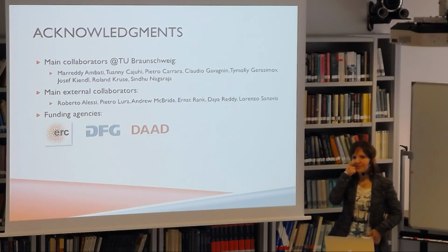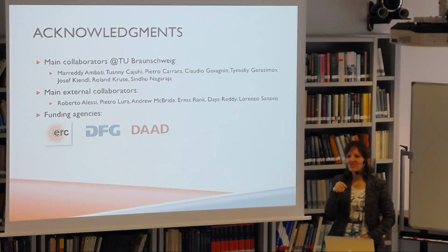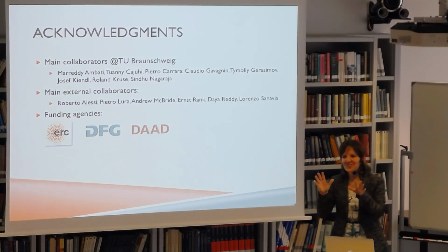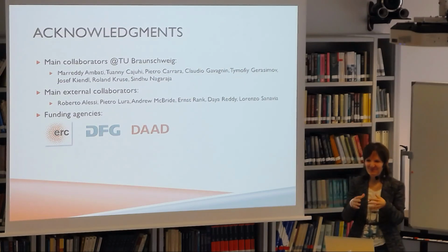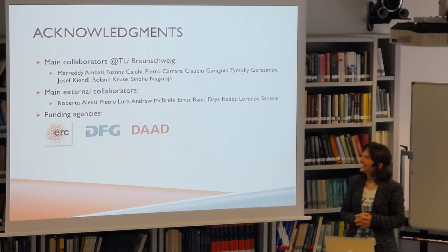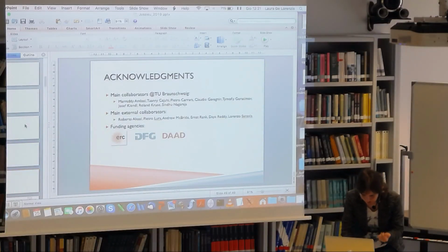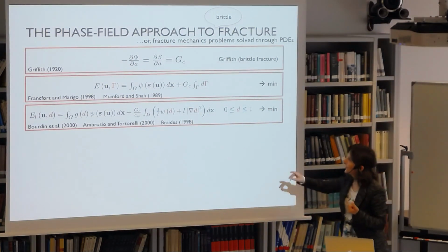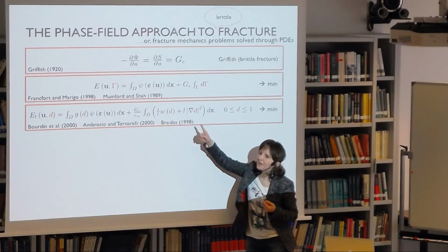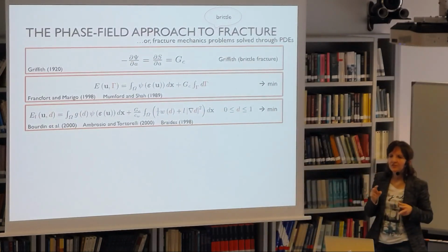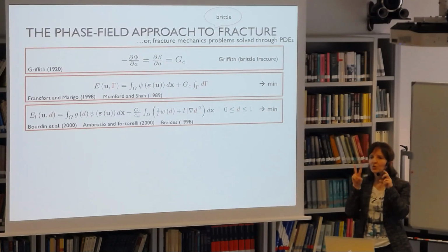Yeah, so this is actually very debated in the community. How come that this approach, well, I wish it was my approach, it's Francfort and Marigo's approach actually, the variational brittle formulation. So what happens is that the gradient damage approach, so the regularized Griffith, is richer than Griffith itself. It's richer in the sense that it contains this length scale, which Griffith doesn't have. So this length scale, in a sense, makes a little miracle. This little miracle is that this length scale adds some sort of cohesive-like behavior.